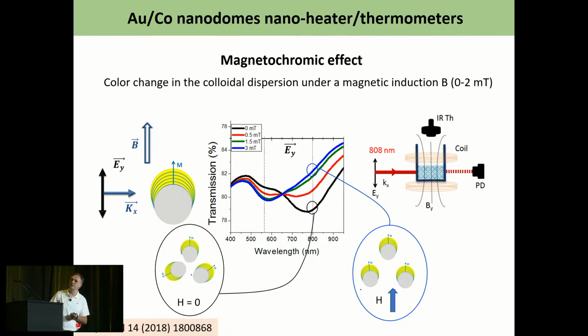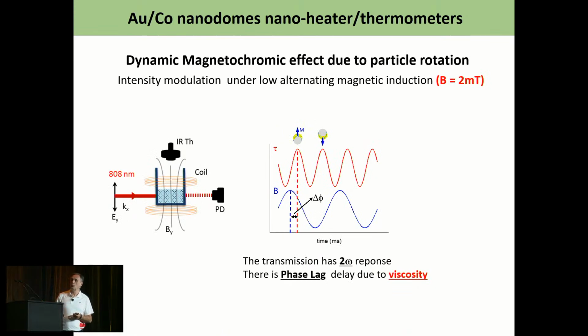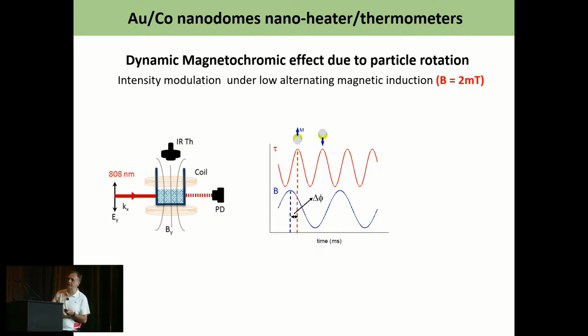We can see here that when the nanodomes are randomly distributed, they have this black curve. And now when we put the magnetic field and the nanodomes align, we have this blue curve. So there is a huge change in transmission just by ordering the particles. So we are going to use this optical anisotropy as a temperature sensor. Instead of having a static magnetic field as we did here, now we put in an AC field.